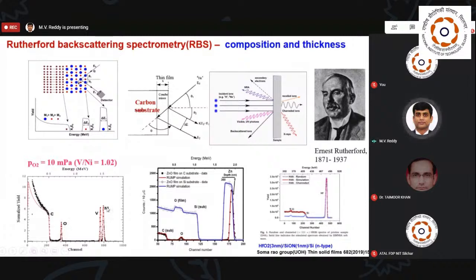You can see that the higher atomic number comes first, or what they call the mass number, atomic weight. Another example, if it's zinc oxide films deposited on a silicon substrate, the substrate comes followed by oxygen, and carbon, like that. Okay, and also it depends on whether it is a thin film or a thick film. And also very important information.